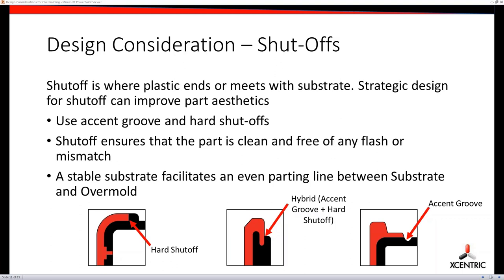All right, we'll take this last one here. If you're having an overmolded part that completely encompasses the substrate on the outside, how do you compensate for the shrink of the overmold as it's being restrained by the substrate? Again, you're creating a tool that's going to have that substrate basically trapped on the inside. One thing you're going to have to think about is that we can't just lay that substrate into that tool. There's going to have to be some sort of standoff, some sort of pin feature, something to lock that in place so that when the material flows into that cavity, it's not going to force that substrate down or away and create some thin areas and so forth.